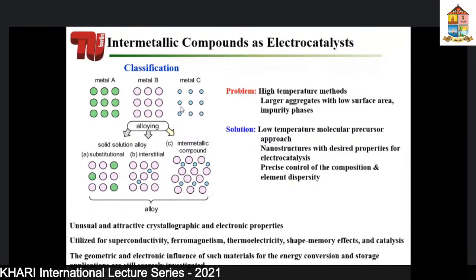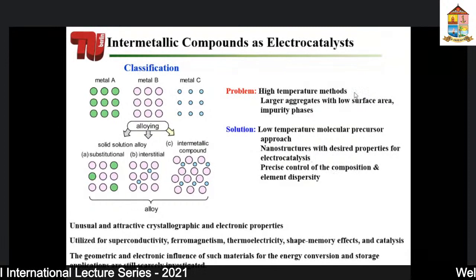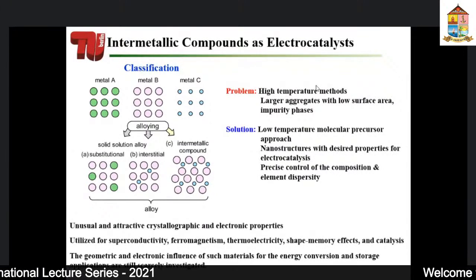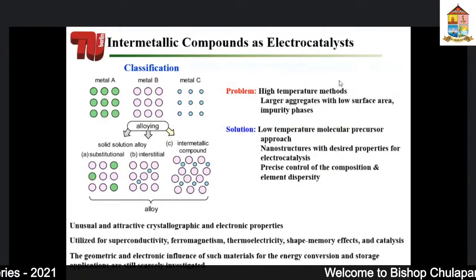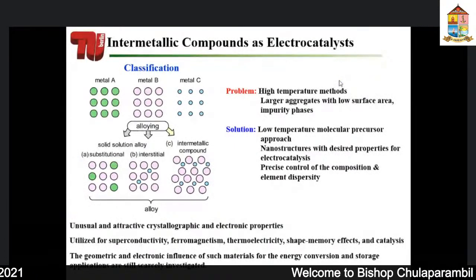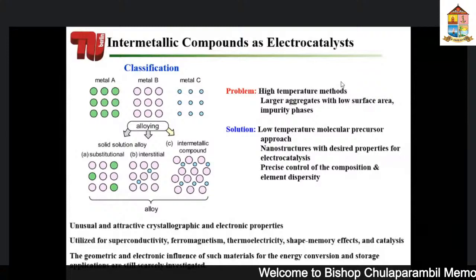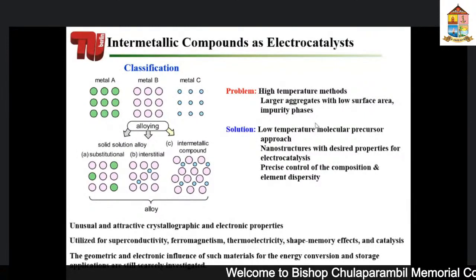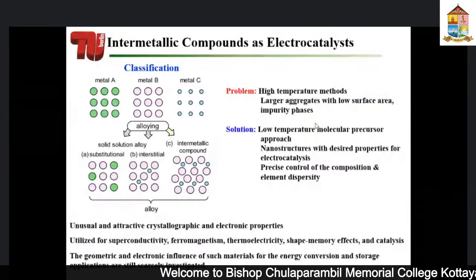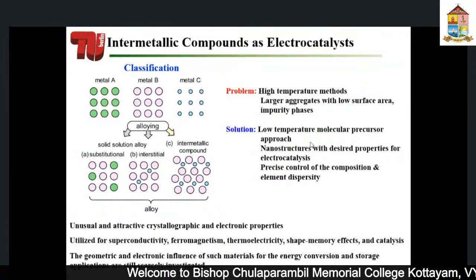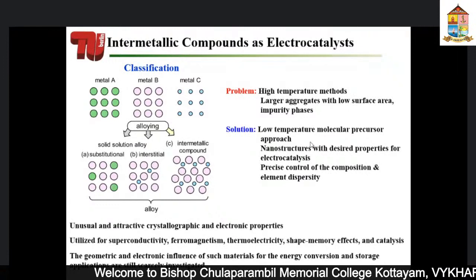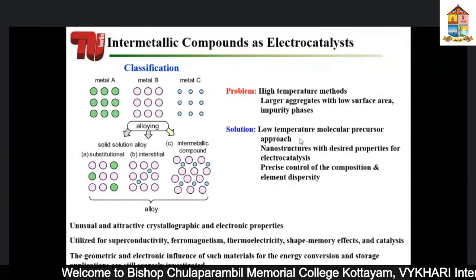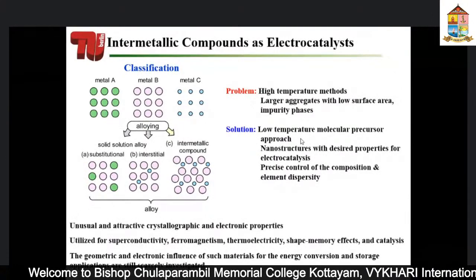Why so? The problem is these materials can only be made by very high temperature methods. That means you're forming very large aggregates with very low surface area, which is quite the opposite of what we need for electrocatalysis. And the problem also is that when you prepare such a material, you're forming, let's say, impurity phases, because you're using very high temperature. You have somehow no control on the complete reaction. The other solution for this problem would be using a low temperature technique, maybe a solution-based one. If we can make nanostructures, it would be great. That could provide our desired properties, what you require for electrocatalysis, such as a high surface area. And by doing so, we can also precisely control the composition and the element dispersity.